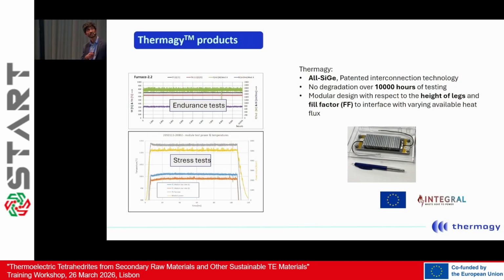Here you can see some of the endurance tests that we have carried out. We have done 10,000 hour tests on the silicon germanium based module, where we have exposed the hot side to 750, 800 degrees centigrade to get up to 2 to 3 kilowatt per meter square. We've also done thermal stress tests where we expose it to higher temperatures, so 1000, 1200 degrees centigrade, to make sure that the bonding and the entire module is still functioning. Our architecture itself is quite modular, so we can vary the height of the legs, which I told you is quite important based on the application, as well as the fill factors to interface with the available heat flux.